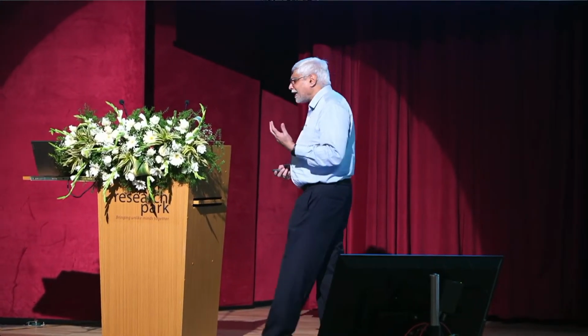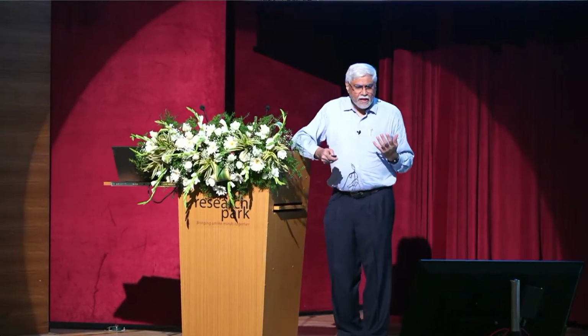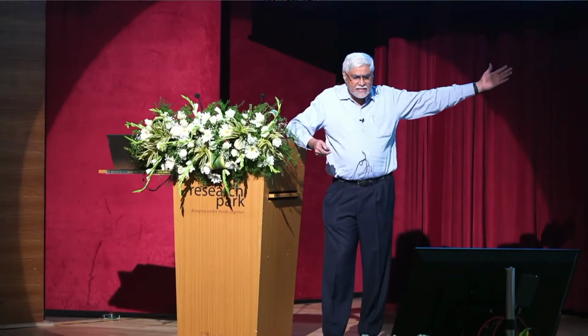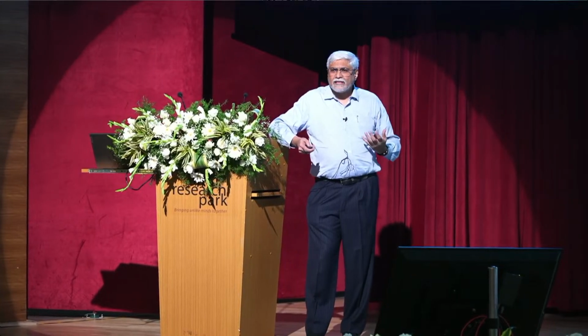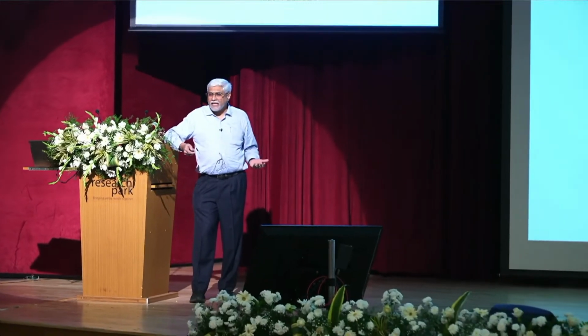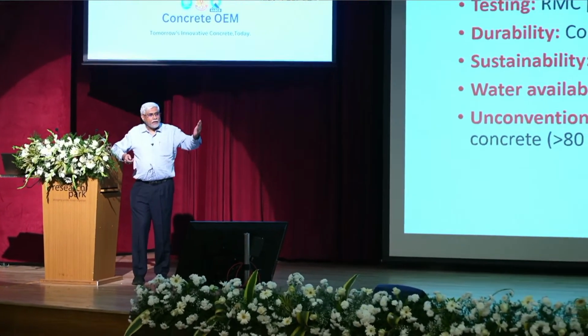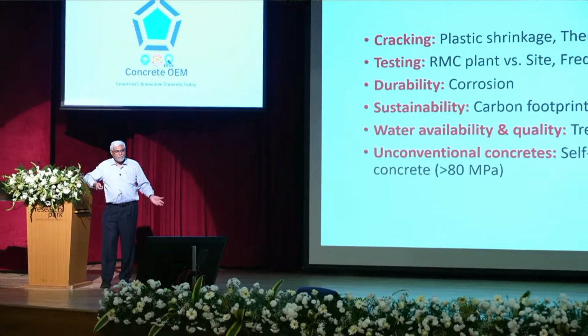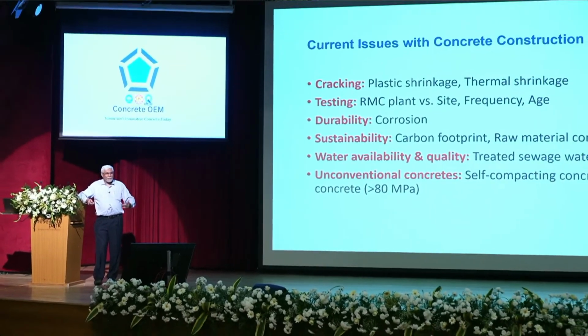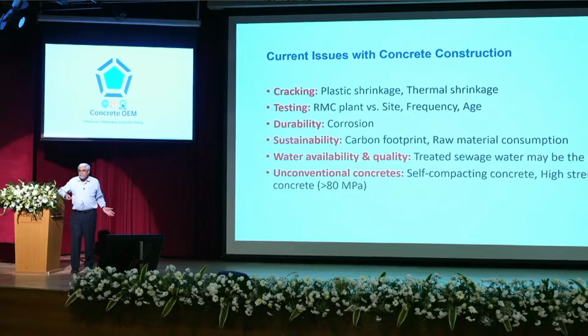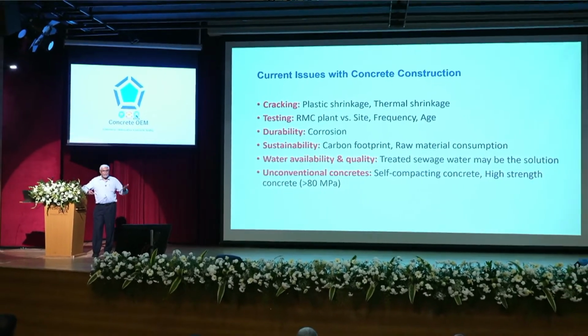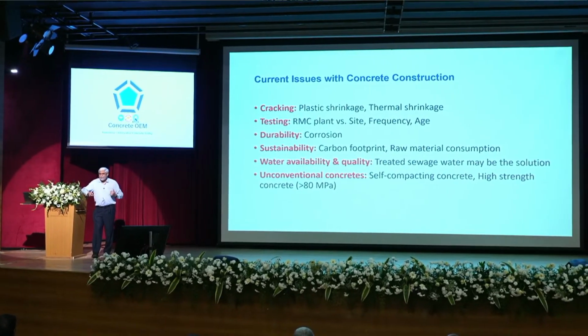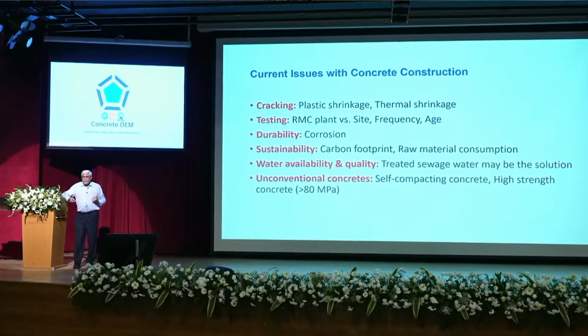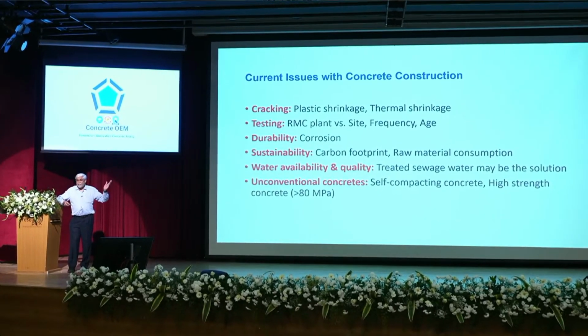So a lot of issues are there with concrete construction today. A lot of you will probably even see more issues, but I've listed some of the things which are of concern. There are a lot of cases of plastic shrinkage cracking. People complain that I used RMC and it cracks. I don't know if concrete OEM will have the same problem, but I'm sure they do not. But generally, this is a concern. Cracking. I'm using RMC, therefore there is a crack. I never got this when I did site-mixed concrete. You have cracks appearing after a week, thermal shrinkage. Where did this thing come from? Long back it never happened.